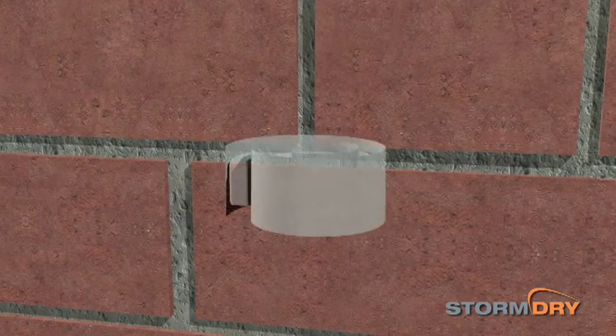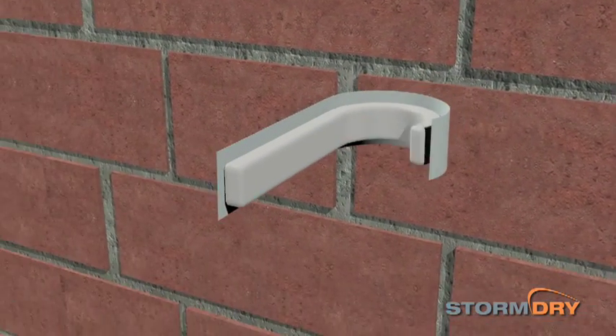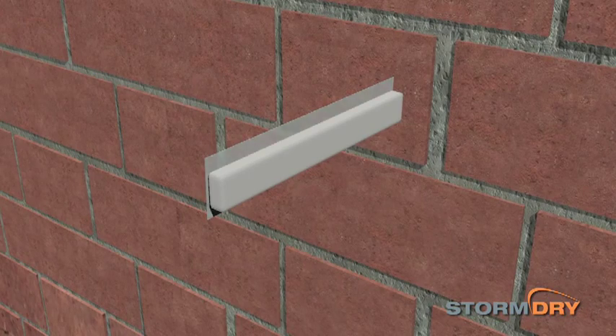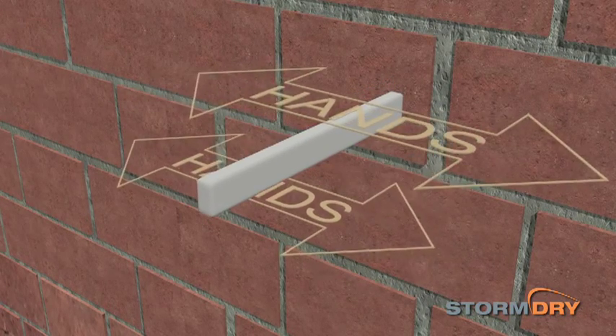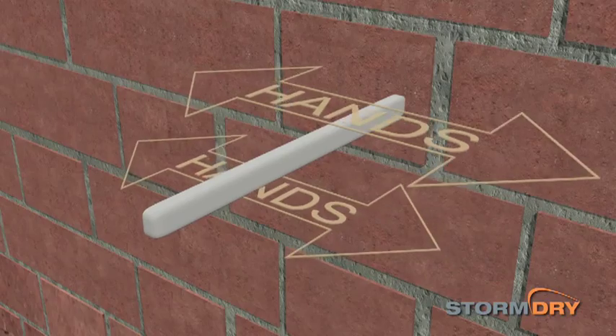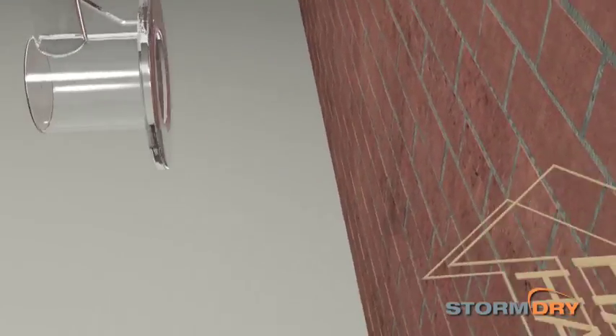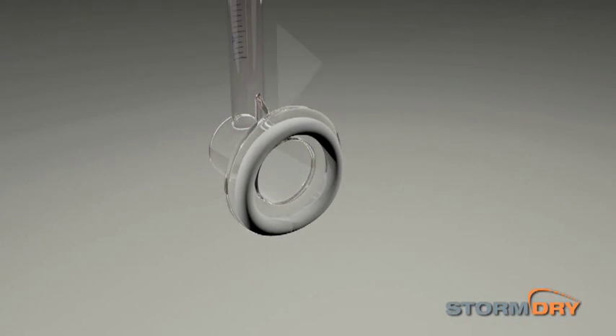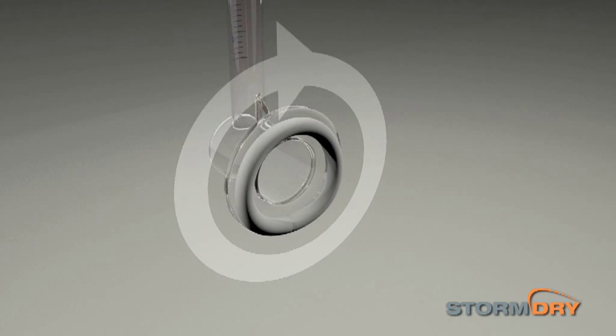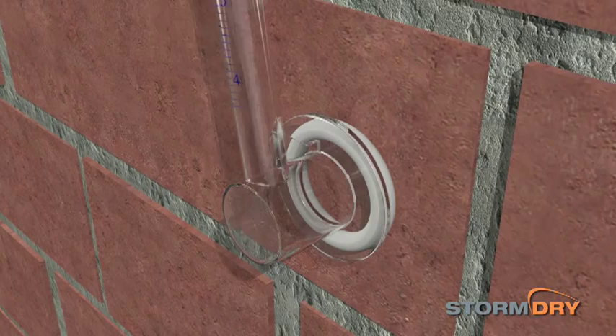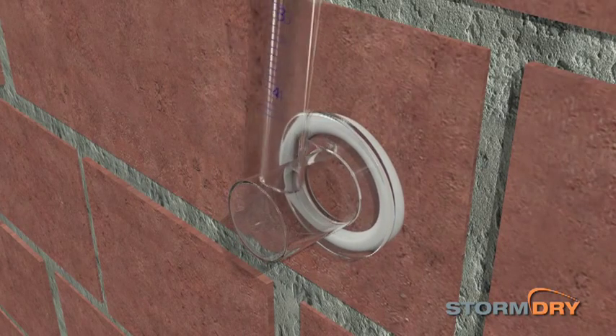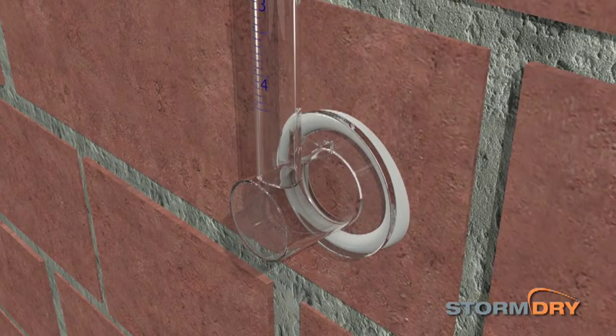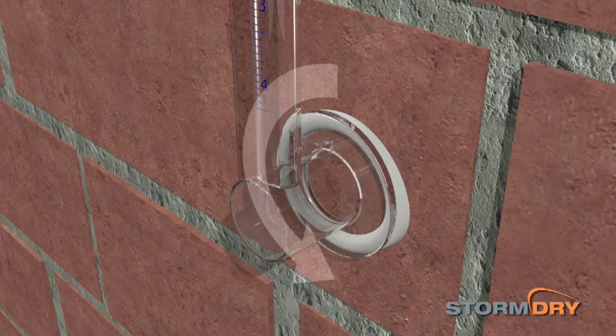Once an area of masonry has been selected for testing, peel back the release paper from the mastic adhesive and roll the sealant between your hands until it is about 10 cm in length. Apply this to the flange of a clean and dry Stormdry gauge, ensuring a complete ring is formed with no air gaps. Press the Stormdry gauge firmly onto the masonry to be tested in an upright position. This may require some force to make sure a good seal is formed.